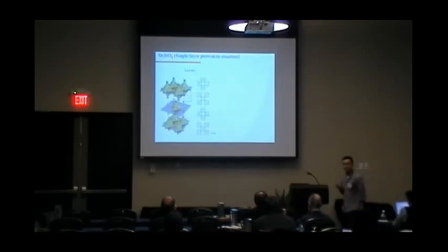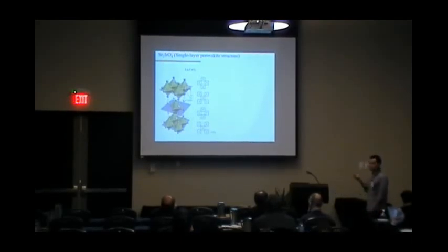I'll spend maybe two or three slides giving you some bare-bones background on this compound. The parent cuprate is a parent compound of high-Tc superconductors. It has a layered perovskite structure consisting of copper atoms that form a square lattice. Each copper atom is octahedrally coordinated by oxygen atoms, and these octahedra are corner-sharing in geometry. If you take planar slices through these copper-oxygen planes, denoted by these gray planes, and project them onto the plane of the board, this is what they look like. You've got copper atoms forming the square lattice, and then a square coordination of oxygen atoms around it. The stacking sequence is as so.